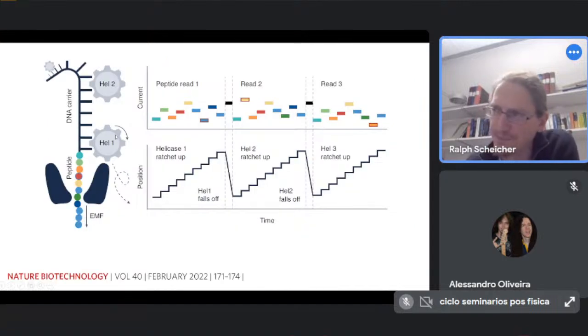So here's a different kind of schematic that shows this more nicely. Basically, it's almost like a ratchet. It moves the DNA upwards, pulls it out of the pore, and then when it reaches the peptide, this helicase doesn't know what to do with peptides. It's not designed to interact with peptides, so it just falls off. But there's another helicase already attached to the DNA higher up on the strand. So then the whole thing is sucked into the nanopore again, and then it's being pulled out again by the helicase. This process repeats and can basically repeat as many times as you want.